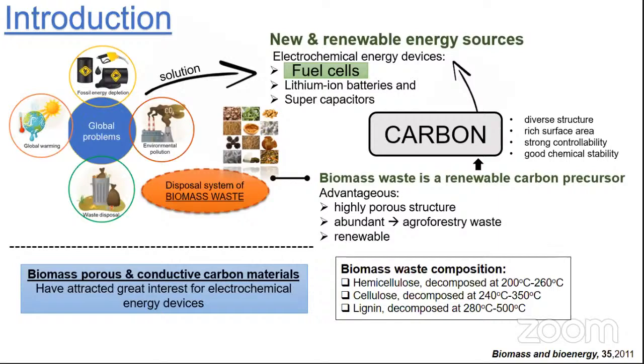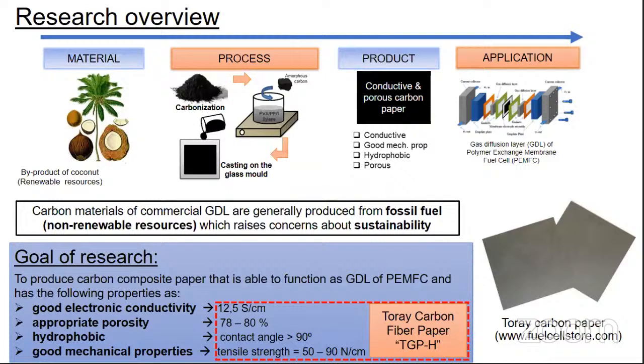And we will focus on the application of carbon in fuel cells. This is our research overview to convert the coconut waste into a value-added product and apply it as one component in the fuel cell stack. For the material, we use coconut waste, especially the coconut coir, that is currently still underutilized compared to other waste. Coconut coir is a byproduct of coconut plantation that is extracted from the fibrous coating of the coconut fruit. Moreover, for the process, we use some steps to transform this waste into a value-added product. At first, we carbonize the coconut coir into conductive carbon material and mix this carbon material with some polymer binder, followed by a casting process on a mold to produce a porous and conductive carbon composite paper with thickness around 0.3 to 0.6 millimeter.